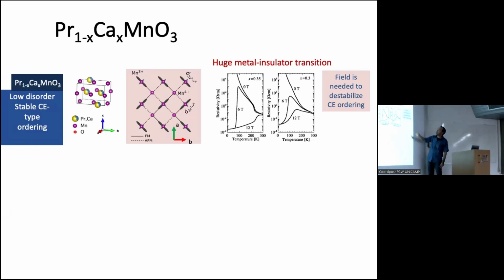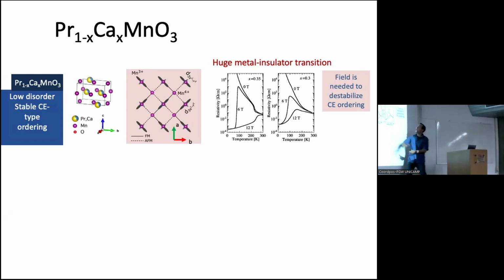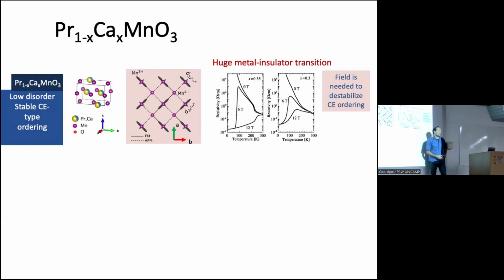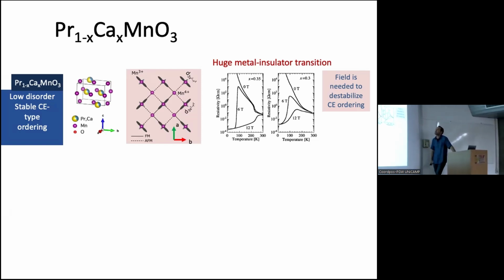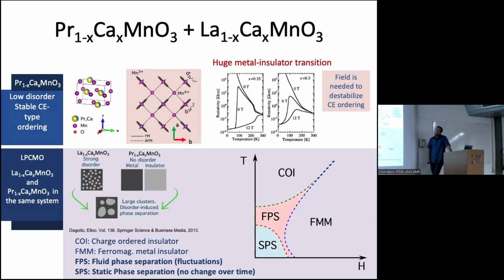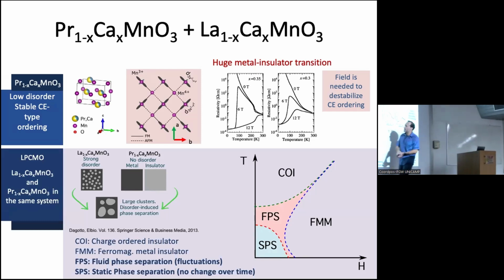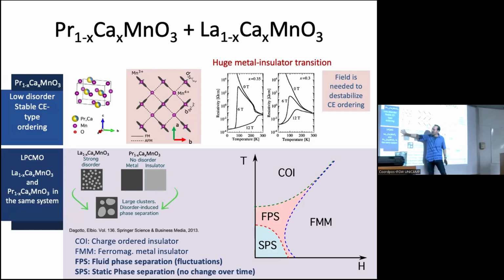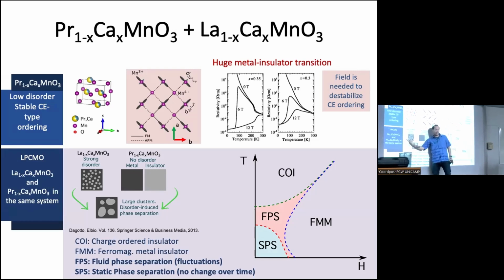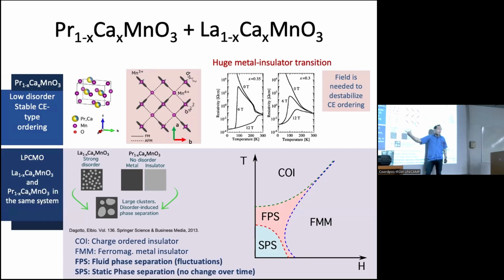But that's not very useful because the fields here are up to even 6 or in the order of 6 Tesla. So that's not very useful. But interesting. So what I'm going to propose here is that we can make a mix of the lanthanum calcium that has these small domains, right? With the praseodymium calcium that has either something that is very metallic or insulated if I apply a field, and mix these two phases together, and what we get is something like this.